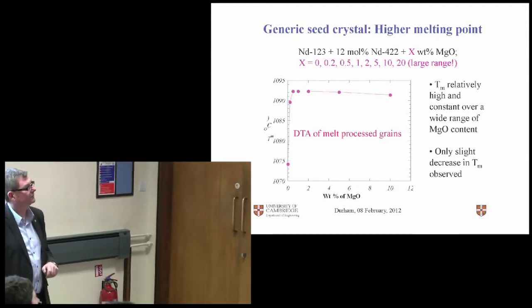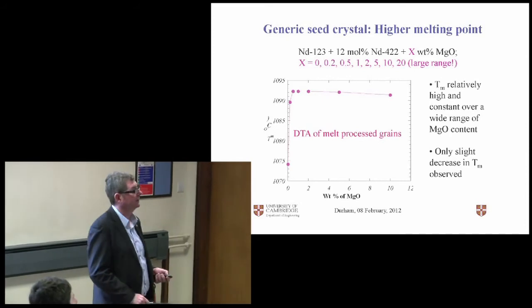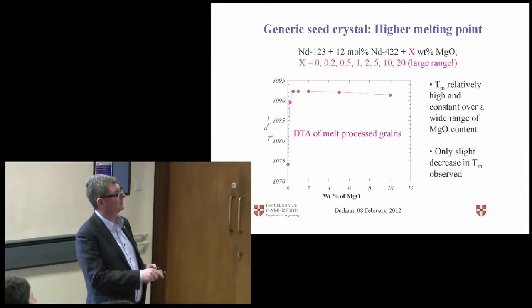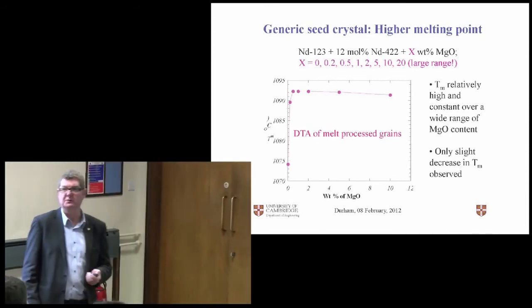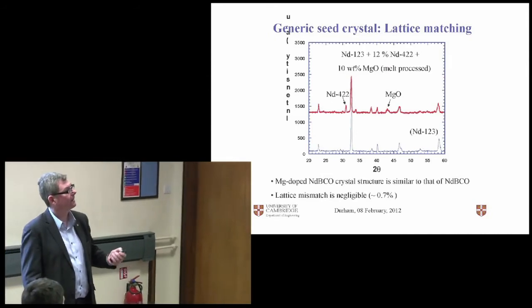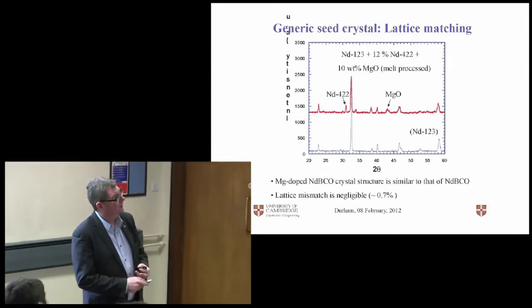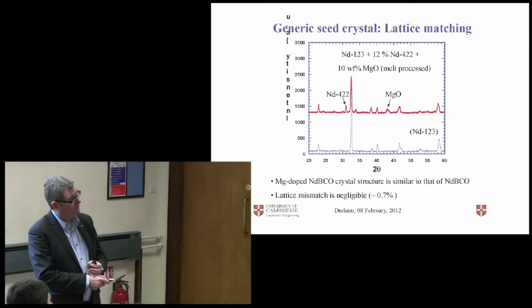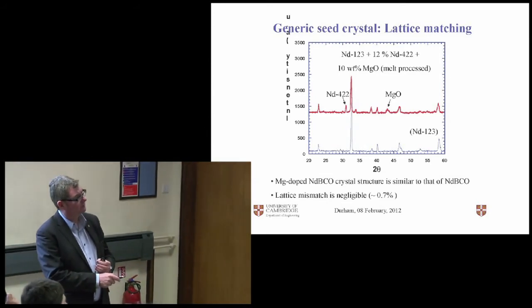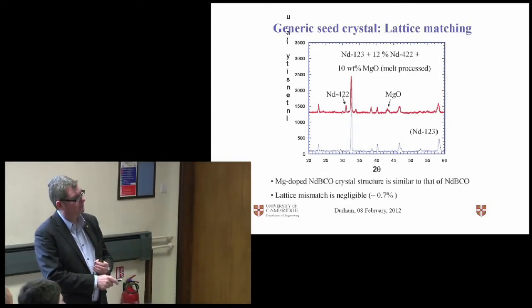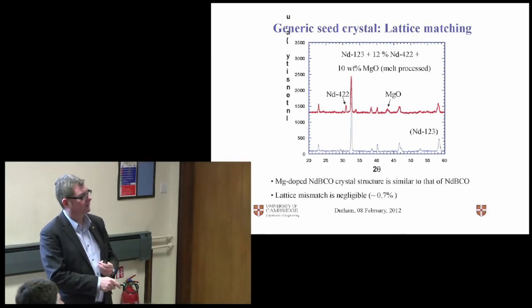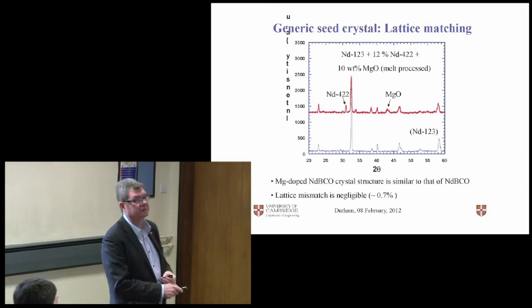The first thing you do is you send them to a different lab, and we did that. In fact, 3 labs have used these single crystal seeds to melt process their own materials. So other properties, lattice matching. So here we've got our magnesium doped seed. At the bottom we've got our neodymium 123. You can see there's a very good lattice match. The peaks are in the same position. In fact, it's less than 0.7%.